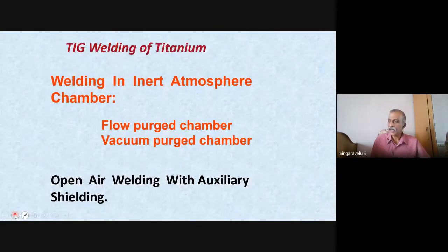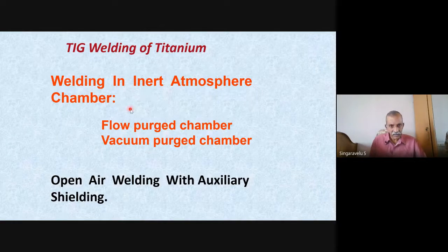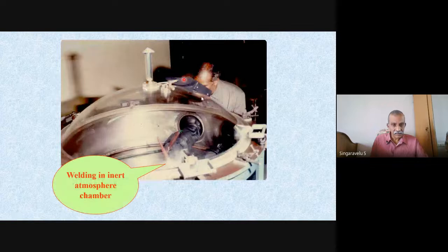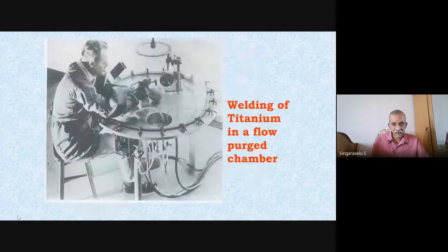So how can these be achieved? All this shielding can be achieved if you do the welding in an inert atmosphere chamber, a flow purged chamber or a vacuum purged chamber, or we can do welding in open air with auxiliary additional shielding. Okay. So this is something with the inert atmosphere chamber. This is called blue box welding, where the air in the entire chamber has been removed and an inert atmosphere like argon has been pumped in, like our COVID test. Like that the welder has to put his hands inside, take the torch inside, and do the welding here. Okay. So in this way, the root, additional shielding, tailing, all these things have been taken care of. Okay. This is another setup like that.